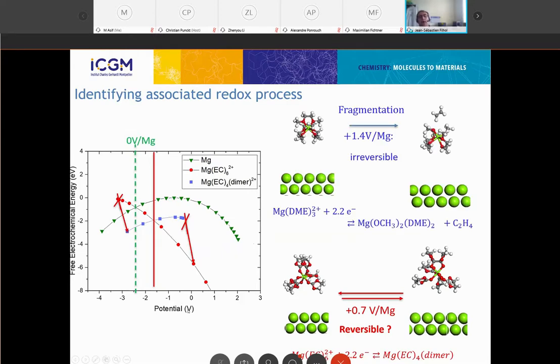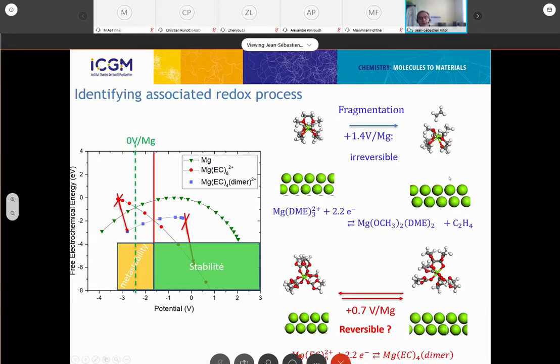And this also occurs for the DME molecule, but this time with fragmentation. And of course, the fragmentation is irreversible. When the fragmentation occurs, there's no turning back because the ethylene molecule cannot find its way back to reform the initial DME. And this is also associated not with the reduction of the magnesium, but a reduction of the DME molecules. So we can already define a stability domain where the solvent is going to be stable, but we have another domain where the solvents will be only metastable. We can find it, but it's not the most stable species. The most stable will be either the dimer or the decomposed DME molecules. And anyway, above a limit, there's no stability at all of the undimerized or unfragmented solvent; they will just become unstable. So there's a stability limit for these systems.